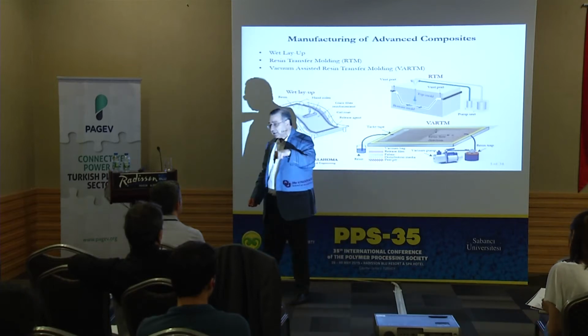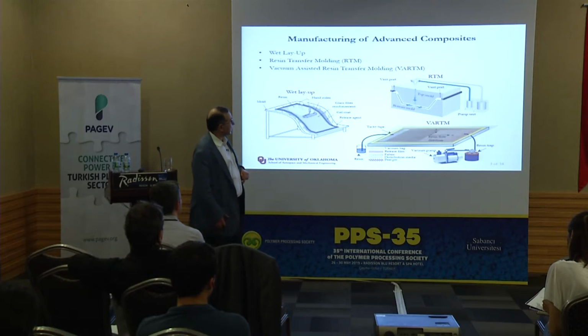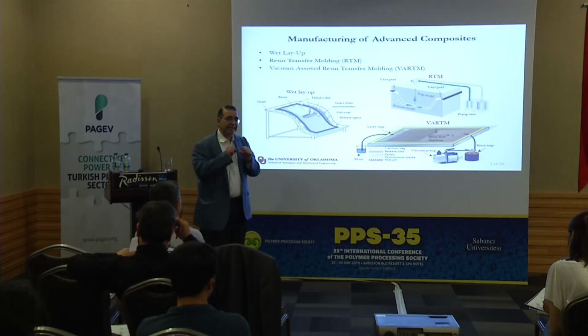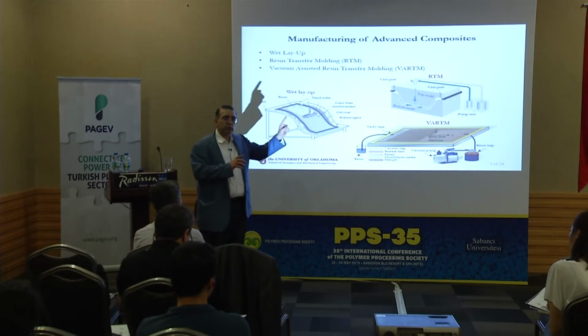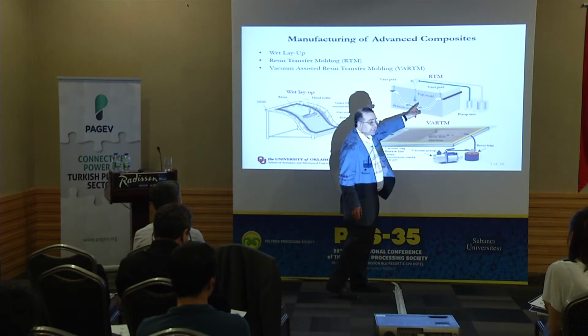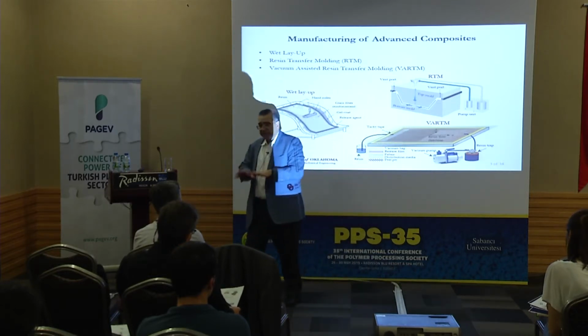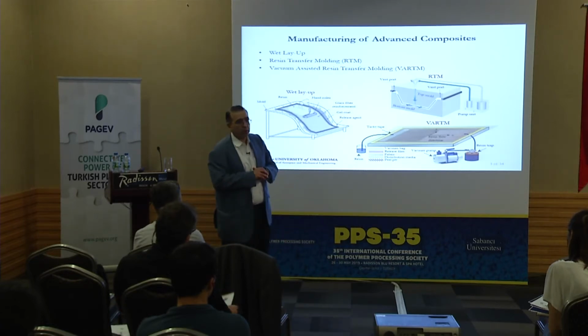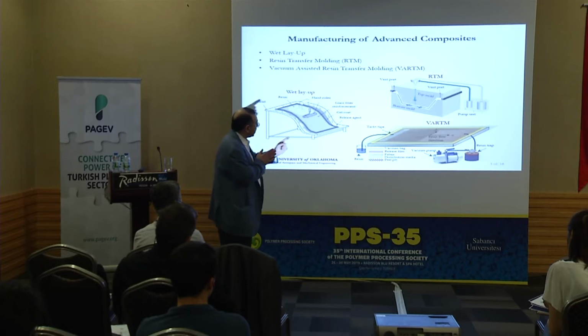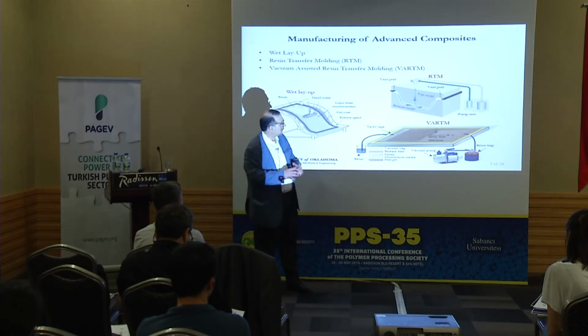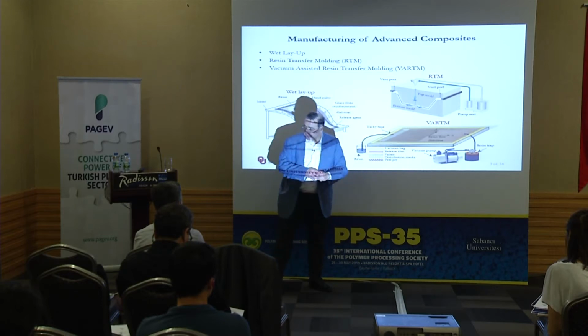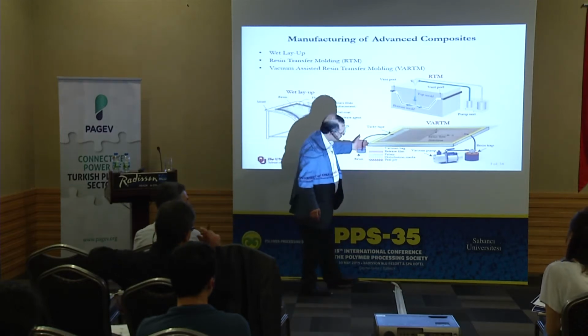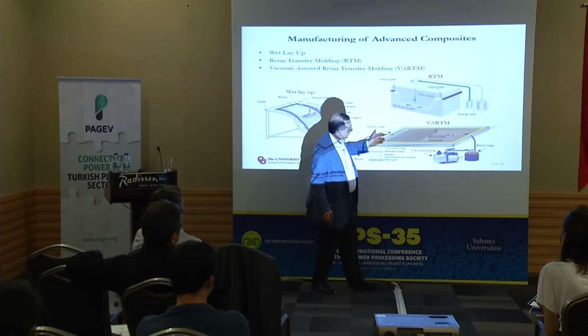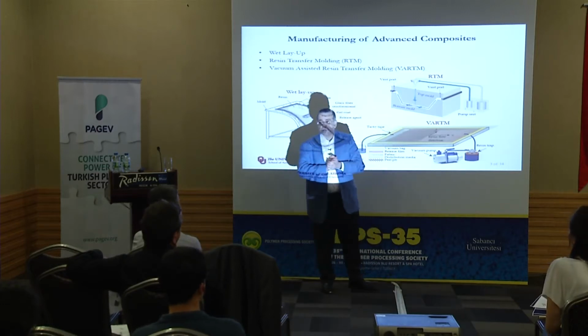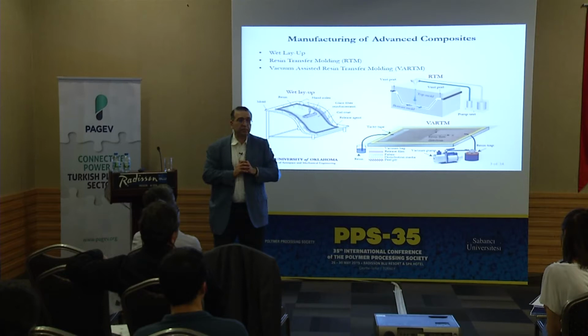In RTM the resin is injected under pressure. Since you are injecting under pressure, you can impregnate a denser or lower permeability fabric, so the fiber volume fraction here will be higher. You can essentially put a lot of fiber into the mold and inject under pressure. Here, the pressure is only vacuum pressure because of the vacuum bag. So the fill time is important, because the filling only takes place because of the vacuum. It is pulling the liquid resin, so viscosity becomes extremely important.